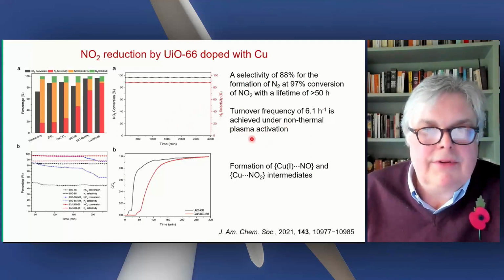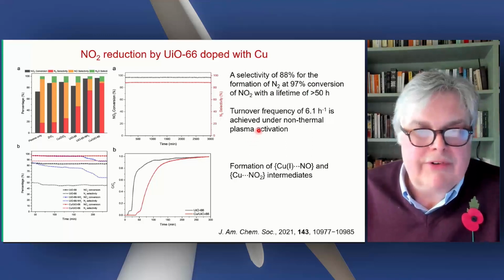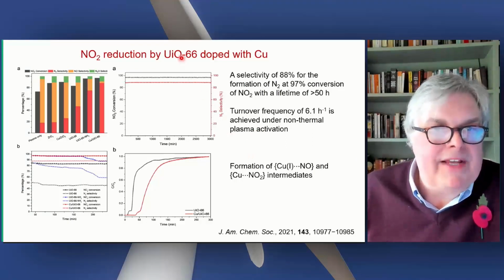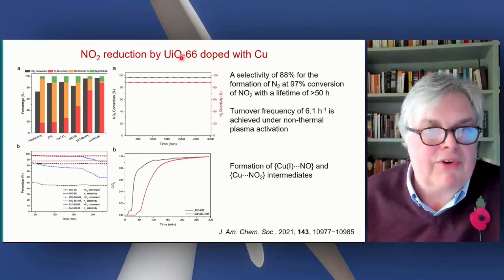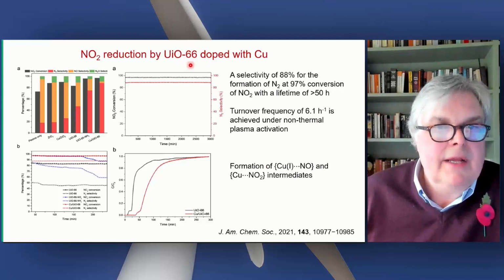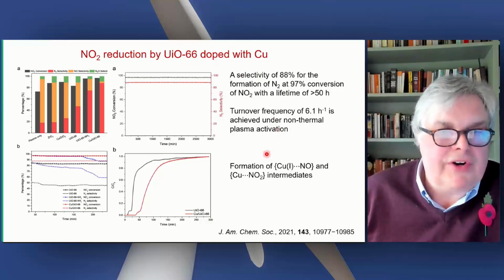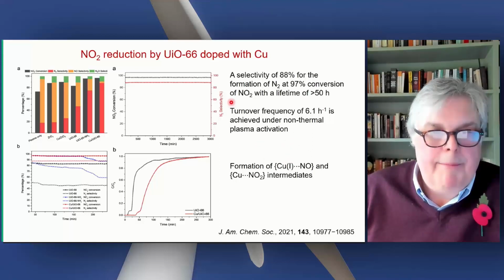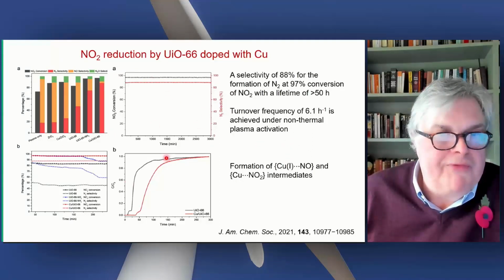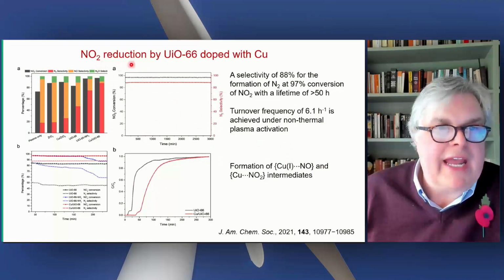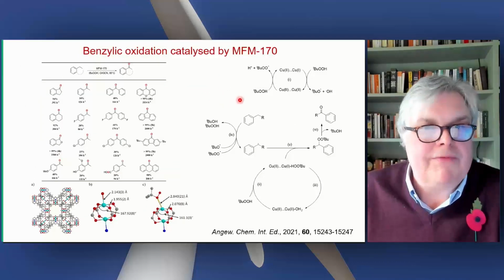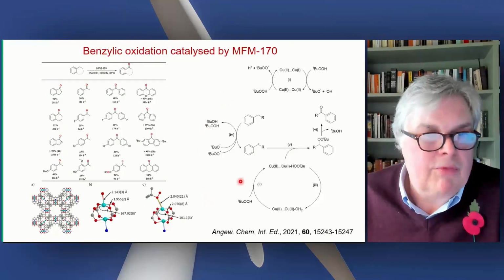It's not done thermally at 300 or 400 degrees centigrade. Many of these MOFs, though, are stable up to 300 to 400 degrees centigrade, but catalysis at that temperature is a challenge for MOFs. But again, this is a proof of principle in terms of looking at NO2 reduction using MOFs. And I finish with some recent work.